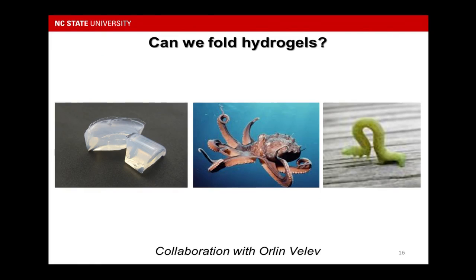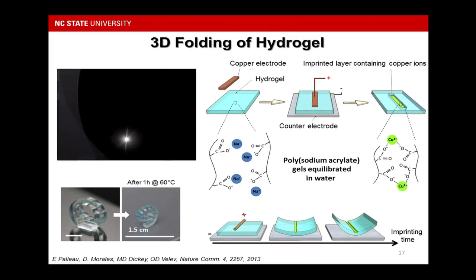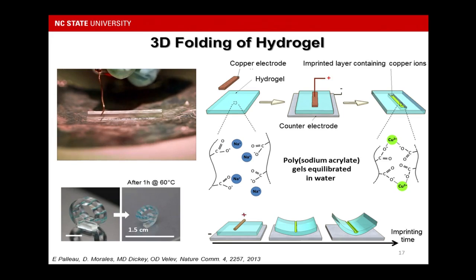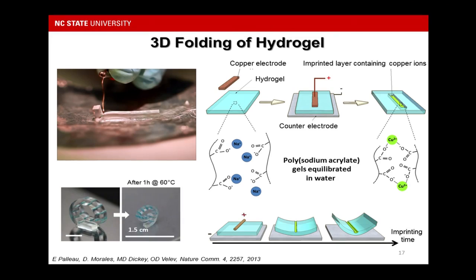The last thing I want to briefly mention is the work on hydrogel folding, in collaboration with Professor Olin Velev in chemical engineering. We're using what's called an electrolyte hydrogel, which has ions inside. When you apply voltage using a copper electrode, the copper ions locally form a complex with the hydrogel and meanwhile release water. So the hydrogel locally shrinks to cause this bending. By applying voltage for different times, you can achieve larger folding angles, as shown here.